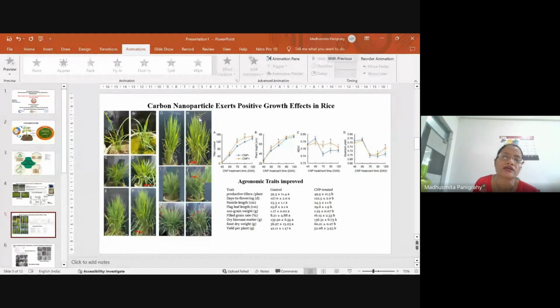Secondly, because Arabidopsis thaliana is a weed, we wanted to try it in rice, which is a model monocot plant. We gave nanoparticle treatment to the rice plant. This first panel is the untreated and the second panel is the treated one, and we have seen that it is showing positive growth effects in the plant by increasing the growth, the tiller number, the height of the plant, the culm length, the number of productive tillers, the number of panicles, and it has also increased the yield.